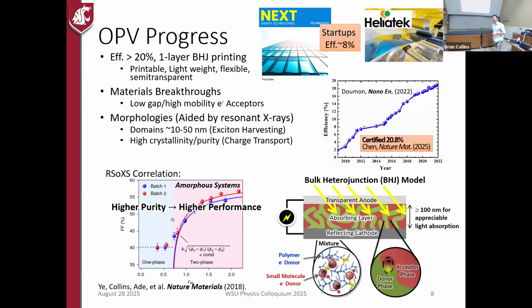Okay. Yeah. So these molecules, I don't have a good absorption spectrum to show you, but each molecule can absorb, and they are chosen to absorb in different parts of the solar spectrum so that they can potentially even beat the Shockley-Queisser limit because they have two different band gaps. But they typically are narrower than, say, silicon. So you typically need two of them to span the entire visible spectrum, going from, say, 400 to, they're pushing to 900 nanometer wavelengths, whereas silicon's band gap is at about 1,000 or so. No ultraviolet, less infrared. Yeah, a little bit less infrared. The chemists are pushing it further into the infrared in terms of their absorption capabilities.